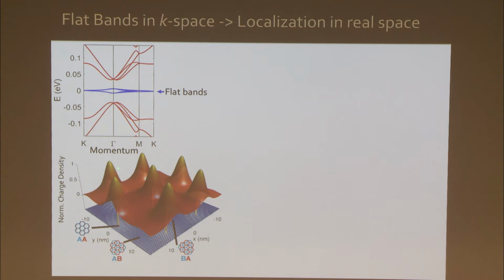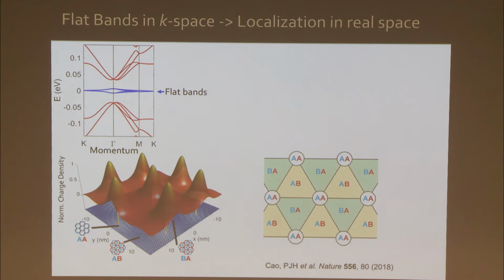In those regions, electrons like to be, and these regions are tunnel coupled by regions that we call AB or BA stacking, where due to the very small twist angle, the carbon atoms go out of registry between the two sheets, and they are sort of across each other. The A atoms are on top of the B atoms of the other layer, and vice versa. So schematically, this is what magic angle graphene looks like. We have these regions of AA stacking where the electrons like to be, separated by regions of AB and BA stacking where the electrons do not like to be.